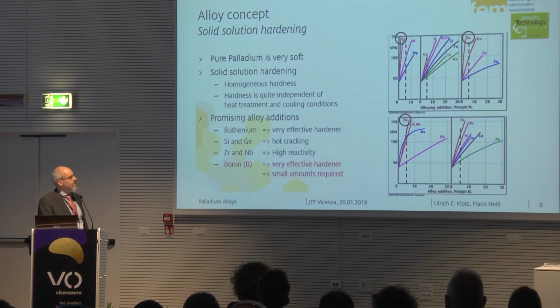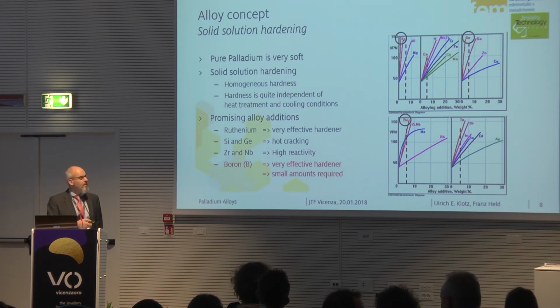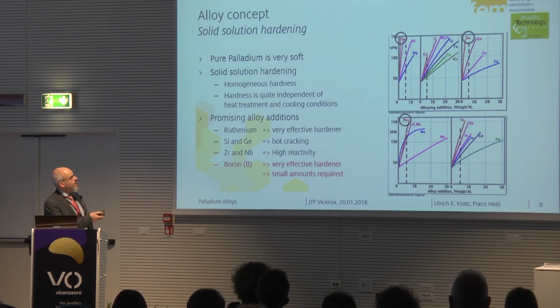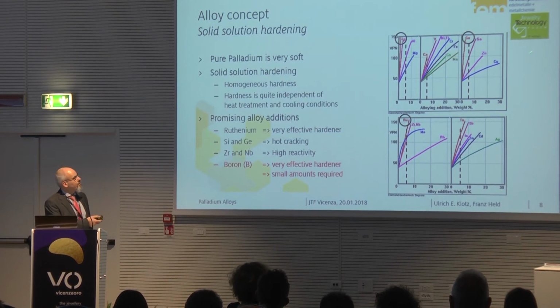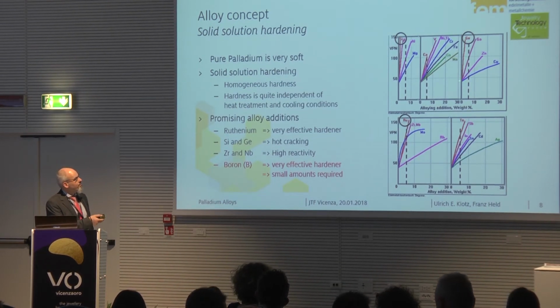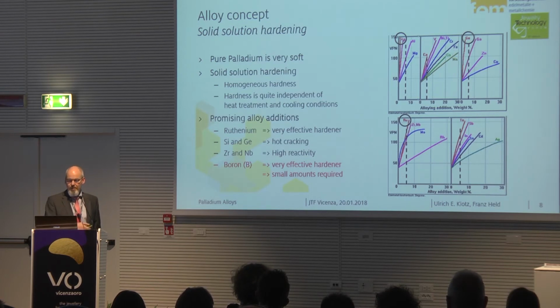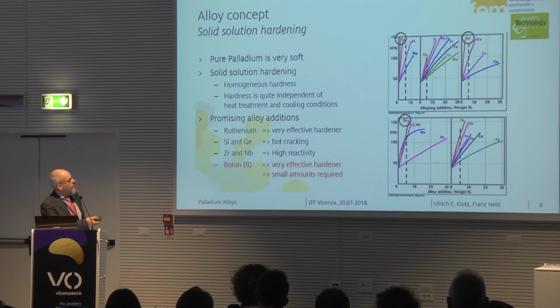Now, if you look in literature, you find diagrams like this. These diagrams show the hardness as a function of alloying composition. And you see there are many possible alloying elements that have different effects on hardness. For instance, if you add copper, the hardness increases along the blue line. Palladium is very soft, pure palladium with a hardness of below 50 Vickers, and copper has very little effect on hardening of palladium. Other elements like gallium or germanium have a much higher effect, so those are interesting because with 5% we want to get into the region of 130 to 160. So we need elements like those that are marked here: silicon, boron, germanium, and ruthenium is the well-known one.